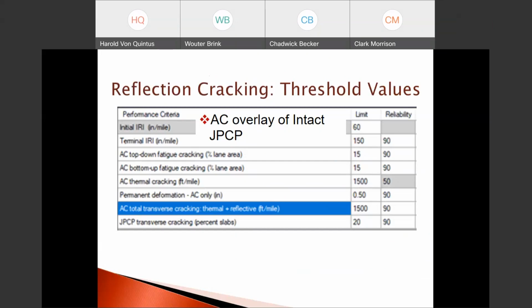It's basically the same or similar. Well, it's not similar to semi-rigid. Basically, the important point here is that as shown in blue in the drop-down screen, AC total transverse cracking, thermal and reflective, should basically be the same as AC thermal cracking new, shown in the above row of this drop-down screen. Those basically should be similar. And then the threshold for the JPCP transverse cracking would also apply, and that's shown as 20% in this screenshot.